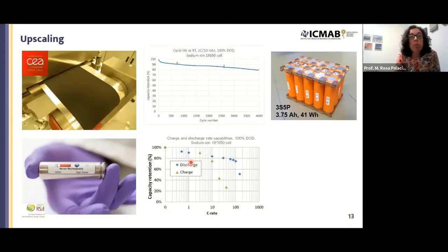So in the framework of a French national project, where we were participating as foreign partners, it was possible to scale up that technology. Here you see the electrodes. These were the cells that were produced. Quite good cycle life for those cells, and also quite good power performance, which was unexpected because it was really the first prototypes, but this sodium vanadium fluorophosphate really reacts with very fast kinetics.